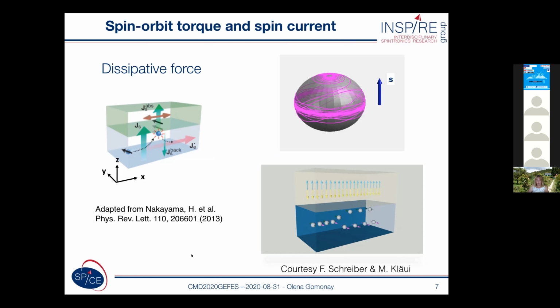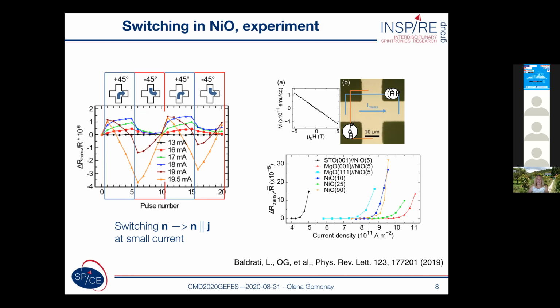Spin orbit torques, for sure, can induce very fast dynamics of antiferromagnetic vectors, but these dynamics cannot induce reliable switching, because the dissipative forces do not remove degeneracy between two orthogonal directions of the Néel vector, and thus the final state in both cases is unpredictable. However, in the experiments which were already discussed in the previous talk, we see clear evidence of the switching between different states.